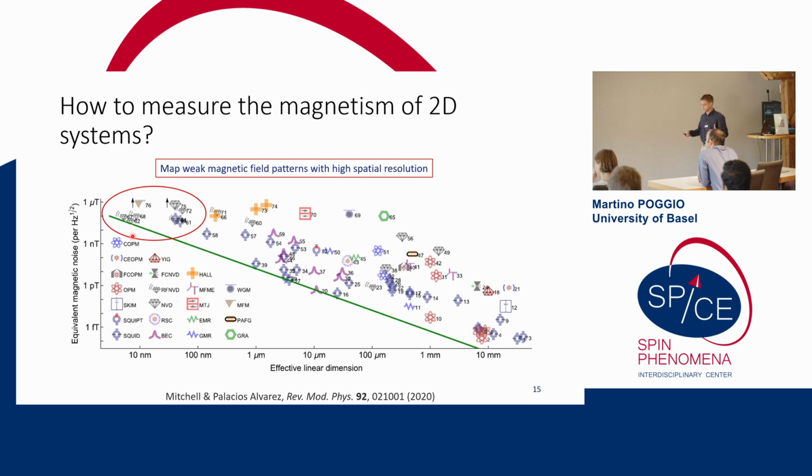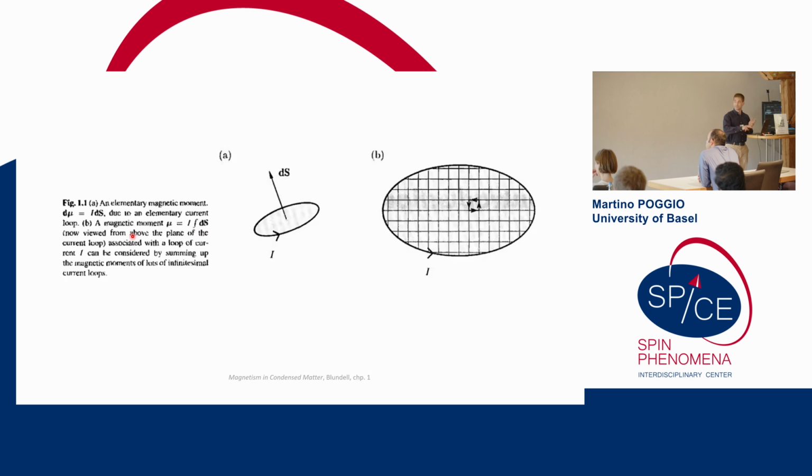So the idea here is we use a scanning probe technique that measures stray field, and then from this measurement of stray field in space, we can reconstruct what's happening in the sample underneath us in terms of the magnetization configuration. Okay, and if you just think about that from a very basic point of view, what does that mean? Let's say I have a 2D plane of uniformly magnetized material. What kind of stray field will I measure from that? And if my 2D plane is infinite, as I guess many of you theorists would like to have a nice uniform infinite plane, the stray field from that above it will be exactly zero. Okay, so you will measure nothing.